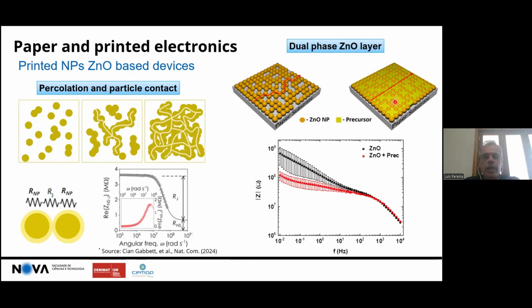But I already mentioned that the precursor may be a problem due to the temperatures and the time required. And here, what we played with was a very low temperature for curing and very fast curing, 5 minutes at 80 degrees, to cure this precursor. We don't need to get a perfect, or I would say a very performing, zinc oxide thin film resulting from the precursor. We just need it to fill the gaps and to improve the percolation. And indeed, you can see that you can reduce by 1 order of magnitude the impedance of a film when you go from this approach to having also the precursor resulting in zinc oxide in between the particles.